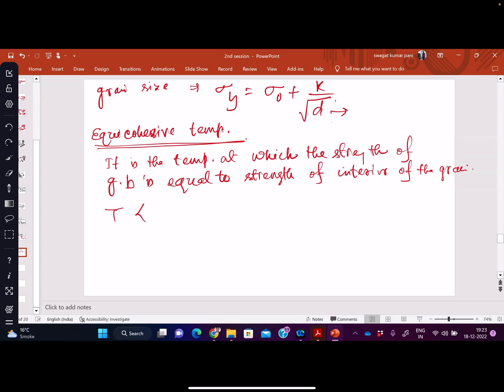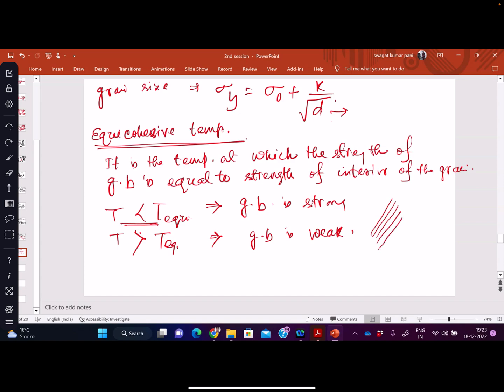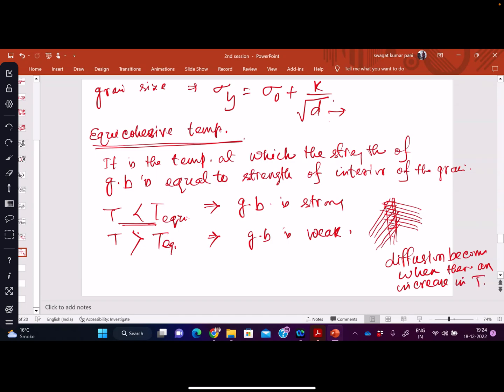Okay, so when temperature is less than T equicohesive, it implies that grain boundary is strong. When temperature is greater than T equicohesive, grain boundary is weak. And why this grain boundary becomes weak at high temperature is because grain boundary has more random structure. Suppose this is interior of one grain and this is other grain. So this is the grain boundary region. There are a lot of open spaces. So what happens? Diffusion becomes easier when there is a slight increase in temperature. So as we go on increasing temperature, these become the easy diffusion paths. So these become weaker. So grain boundary sliding takes place.